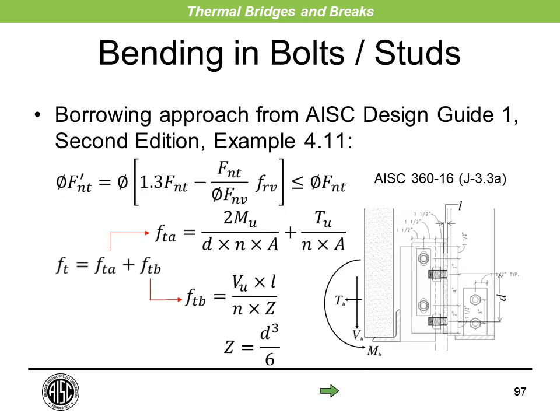So how do we design for these kinds of things? Well, the Northeastern study found that relatively thinner insulating shims, less than about an inch in thickness, generally had less impact on the strength and stiffness of the connection than thicker shims. And I think that's a relatively obvious conclusion. And they verified this through some physical testing that we did here in our laboratory, as well as through some finite element analysis done using Abaqus. And they concluded that while the bolts dictate the failure, the shim's influence on the overall behavior permitted additional displacement of the system and also decreased the connection stiffness.